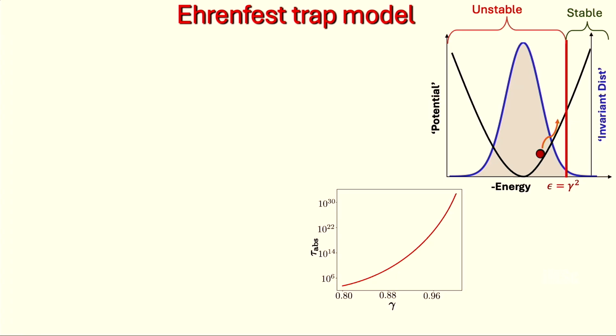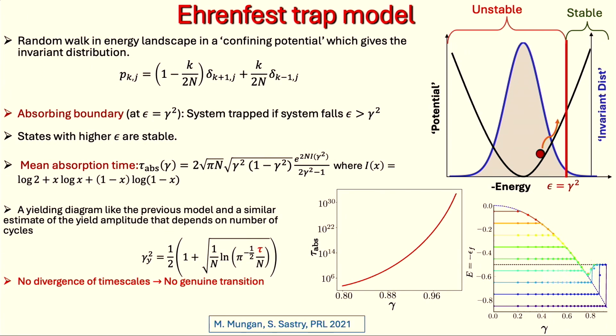And so for any amplitude of strain, I have a boundary beyond which the system will be stable with respect to a cycle of shear. But for smaller energies, it will make a transition to a new minimum. So I can therefore ask the question, how long does it take the system to reach this threshold? So this is now a very standard problem of first passage time, and the answers are known. So there is a time scale which I call the absorbing time, which is growing very strongly as I shift this boundary further and further to the right.